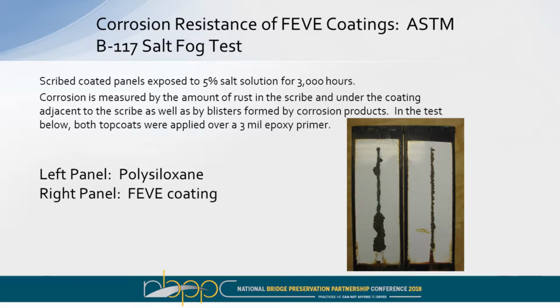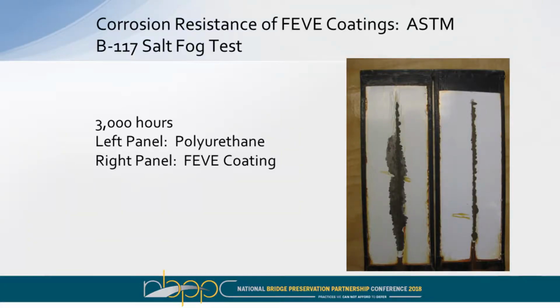This is ASTM B117, just visual. I don't have any blistering information on it, but you can see visually that the FEVE coating does seem to have better corrosion resistance than the polysiloxane does. Just visual again. Same thing here with the polyurethane, and the same thing you can see there.